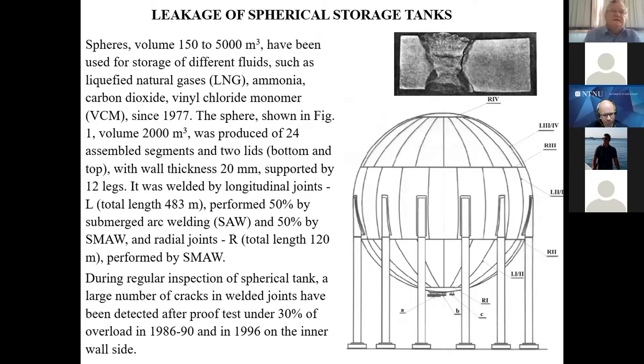although certainly weldable and certainly not problematic if welding procedure specification is followed strictly. Now, in real life, it happens from time to time that welders do not follow instructions. They do not dry electrodes, for example. So hydrogen cracking was not an uncommon problem in this type of steel and this type of construction.